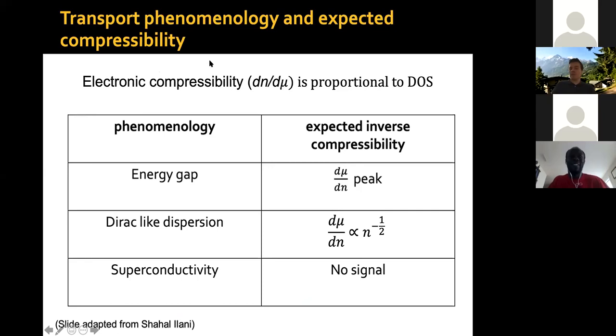Now, the thing that we measure in our experiment is inverse compressibility. So we measure dμ/dn. So how does the chemical potential of your system change when you add particles to your system? So this is the phenomenology, and what is the expected inverse compressibility signature? For example, if you have an energy gap, because an energy gap means no density of states, you would expect zero compressibility and therefore a peak, infinite ideally, but usually a peak or a maximum in the dμ/dn.